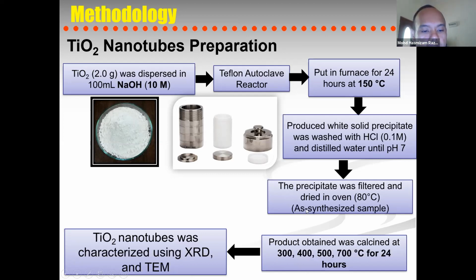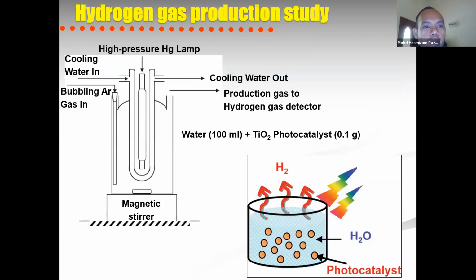The product is then characterized using XRD and TEM to confirm the formation of nanotubes as well as titanium dioxide. Then the product is tested for hydrogen gas production. Very straightforward reactions: we have our photocatalyst and we have water, since we use water splitting reactions. We mix them together and expose to UV light for 5 hours, and every 1 hour we measure the hydrogen gas produced using a hydrogen gas detector.